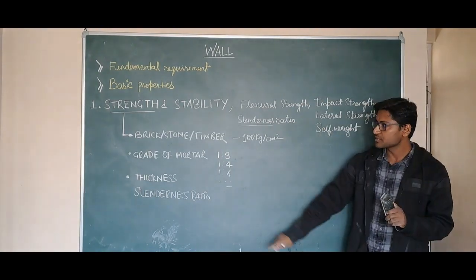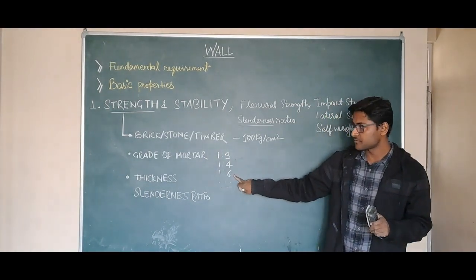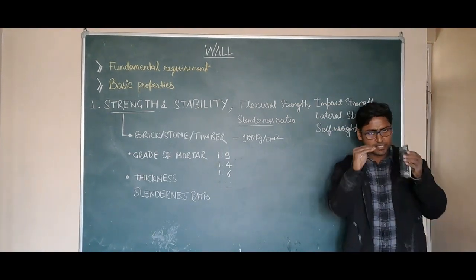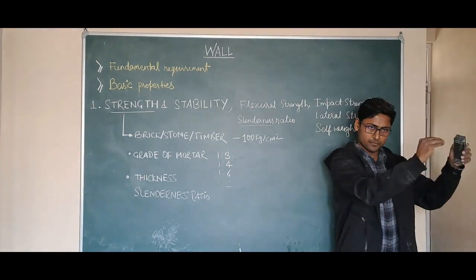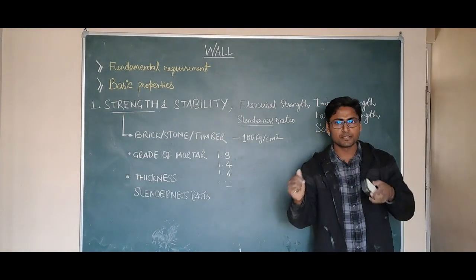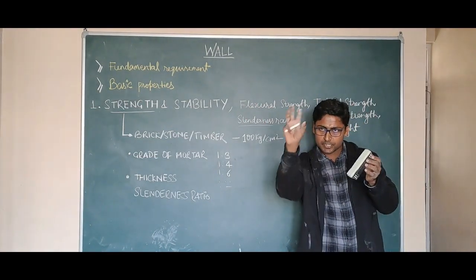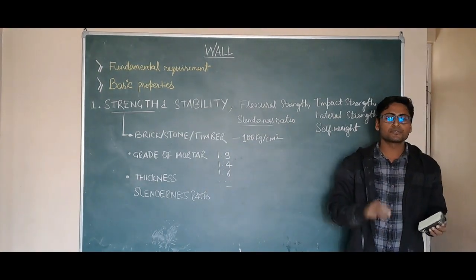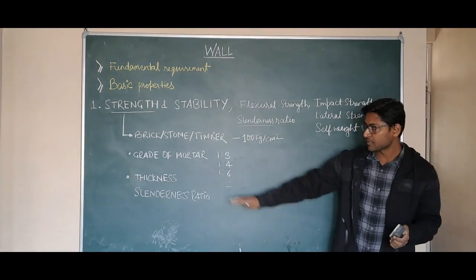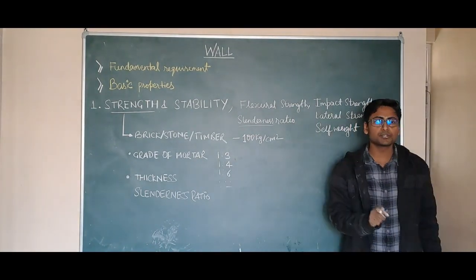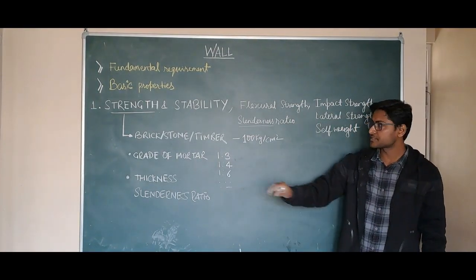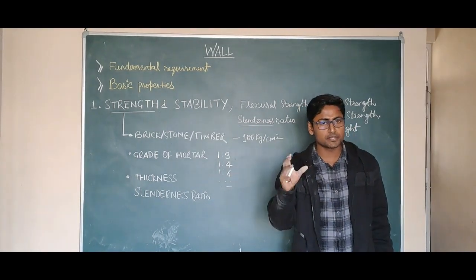So if you are using the porous or a little bit weak mortar in nature, less cementitious material, it will take care of settlement. And suppose if a little bit more settlement is there, so the entire brickwork, the settlement will distribute among the various layers of mortar. So instead of having crack in brick, the mortar will take care if you are using a little bit less grade of mortar with weaker brick. Obviously, if you are using high grade of brick, use high strength of mortar.